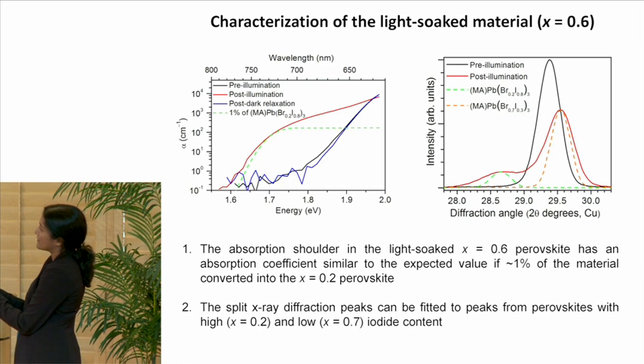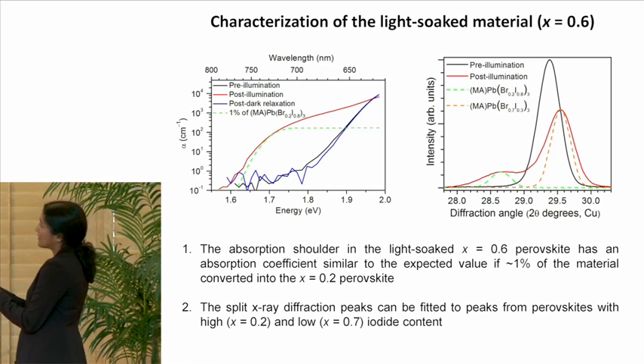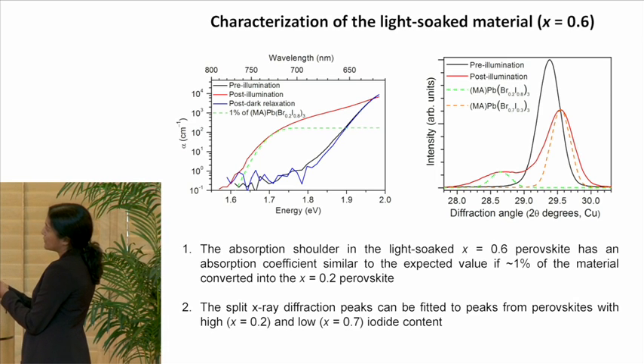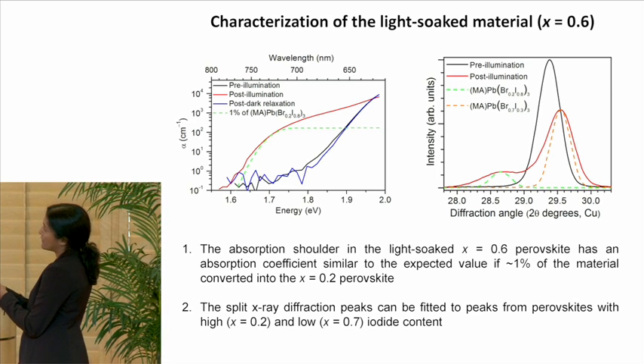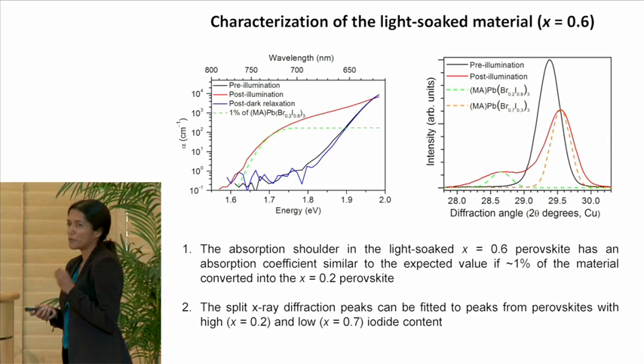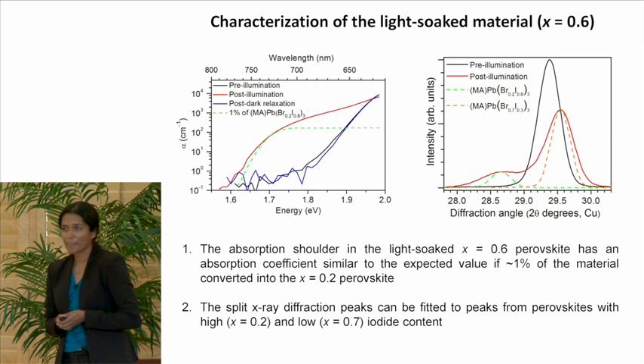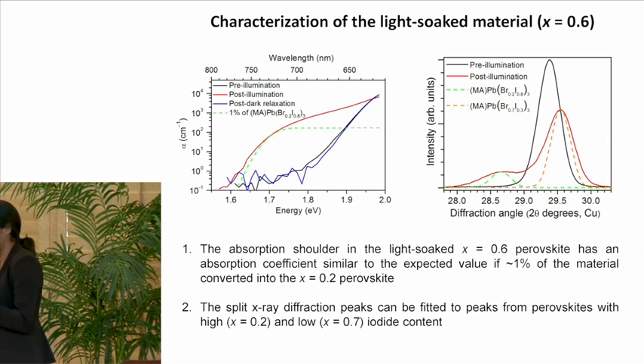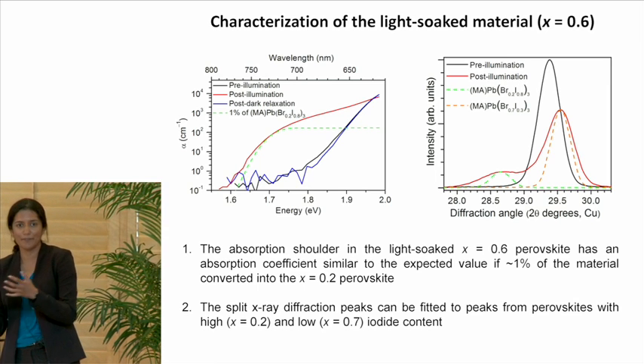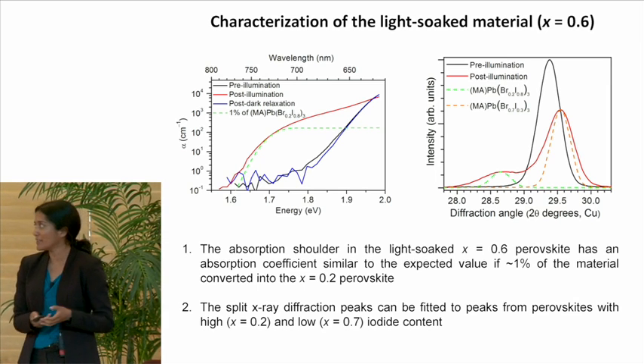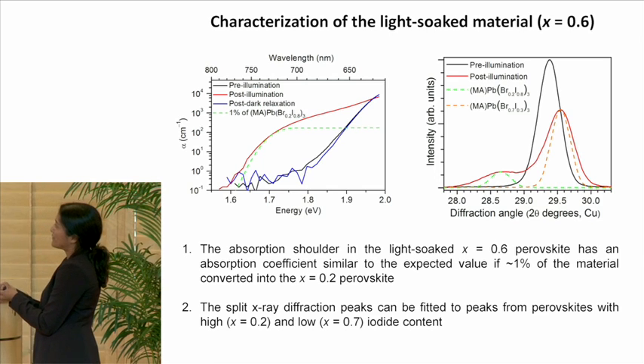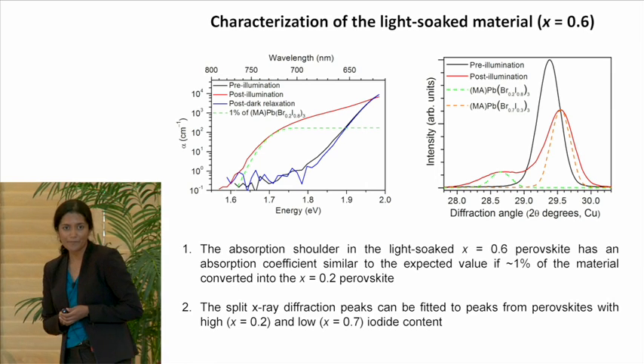If we were to fit this shoulder that we see emerge in the light-soaked material, that actually corresponds quite well to what we would expect from the absorption spectrum of the x equals 0.2 material if about 1% of that material converted. And if we were to form regions of high iodide content, that means we must, by necessity, form regions of low iodide content as well. And that also explains the split diffraction peaks, because here, this peak matches well with the x equals 0.2 material, and this peak matches quite well with the x equals 0.7 material.